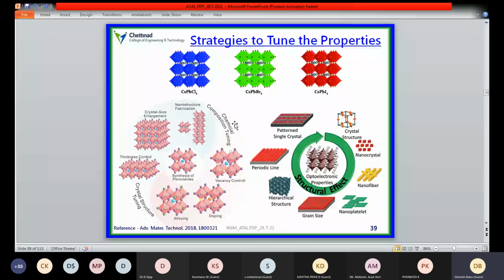So the main important aspect of these metal halide perovskite systems is that their properties can be easily tuned by adopting alloying systems, doping various materials into it, vacancy control, nanostructure fabrication, crystal size enlargement from 0-dimensional to 3-dimensional, and thickness control between the layers of the particular devices. So by adopting these kinds of methodologies, we can get good properties from the perovskite materials. Also, we can fabricate various kinds of structures, the structural effect of these perovskite systems, like fibers, platelets, hierarchical structures, crystals, and patterned crystals, and the single crystal phase can also be fabricated.